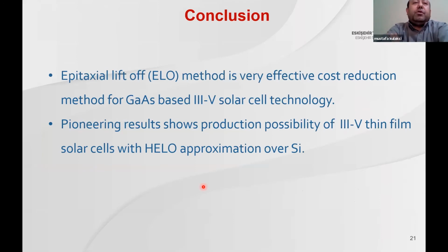So in conclusion, there are two main conclusions here. One of them is that the epitaxy liftoff method is very effective for cost reduction for very functional devices, which means it opens a new route to III-V solar cells. I guess that in future, all III-V solar cells will be converted to the epitaxial liftoff process. And also the pioneering results show that production may also be possible over silicon for a substantial decrease in the cost of these devices.